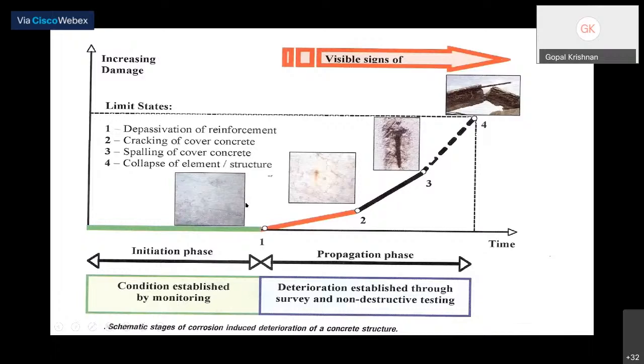The development of corrosion products occupies a volume significantly larger than the original steel. Generally, we say corroded steel occupies a volume 3 to 6 times that of the original steel. So what happens? Cracks form, the cracks widen and facilitate penetration of moisture and aggressive substances into the concrete, promoting a faster rate of corrosion, eventually leading to spalling of the cover concrete. In the second stage, you can say that there is a stain on the surface, but still you may not be able to see any deterioration.